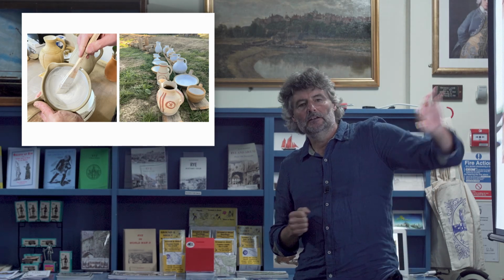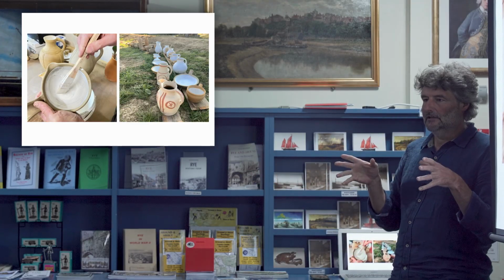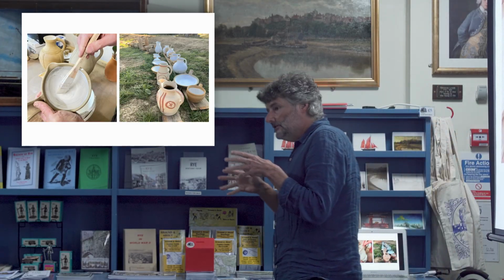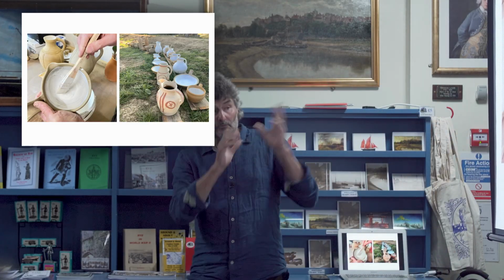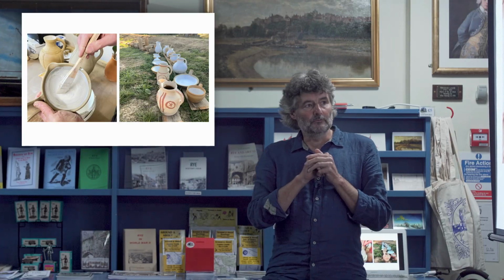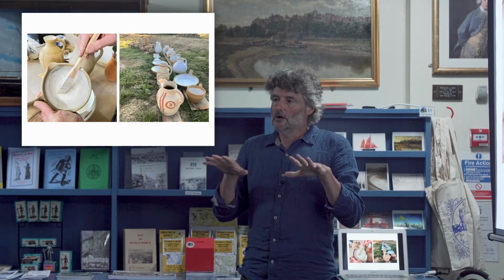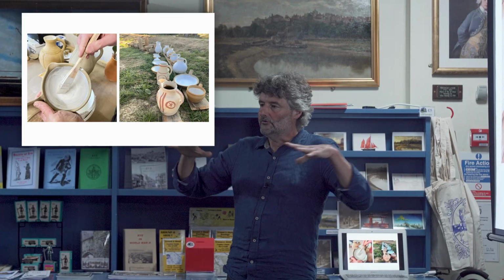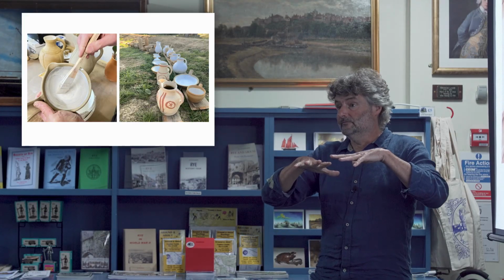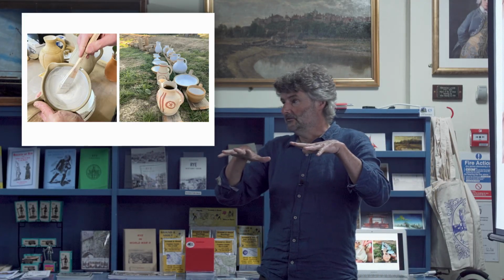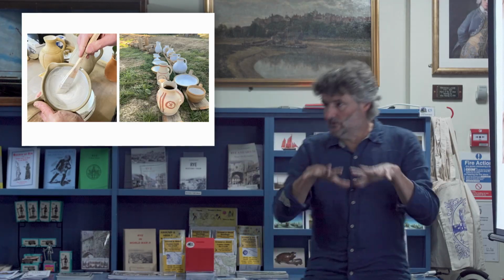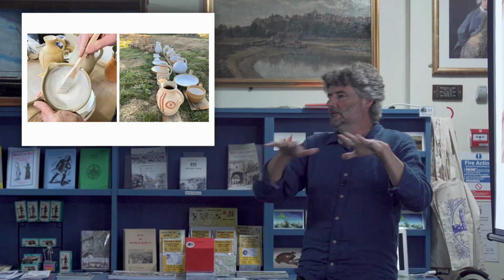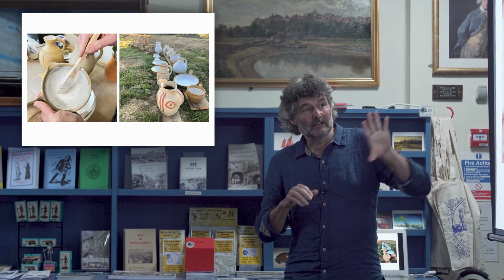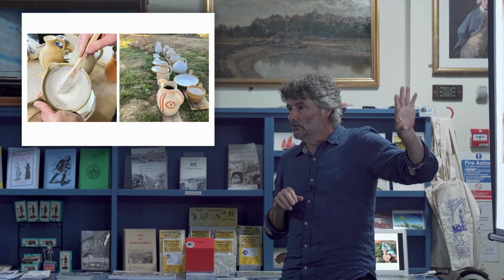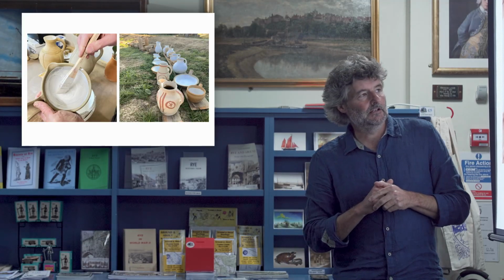So this is a lead glaze, and the reason they would have depended on lead glazes is because at the kiln temperatures that you can achieve with the sort of mud kiln that we've built, it's just about the only substance that will cause silica to melt into glass, which is what makes glaze. So the lead is a very, very powerful sort of flux, and at the temperatures that we're working at, the medieval potters could only really have used that as their glaze.